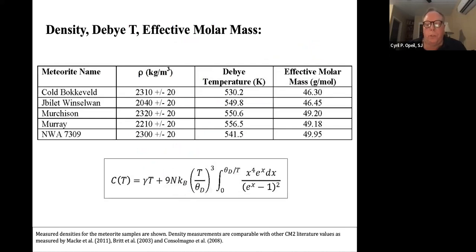I also want to mention that from this data, we can calculate the Debye temperature of each of these materials and also the effective molar mass. The reason I do this is that the Debye temperature is really the highest normal mode of vibration, and it correlates with elastic properties. I think it's important to explore these elastic properties in all materials. From this heat capacity data, you can also calculate the effective molar mass. What's really helpful here is that all of the effective molar masses are around the same. They're averaged about the same. And the Debye temperature is essentially the same. What that tells you is that they're all well behaved.